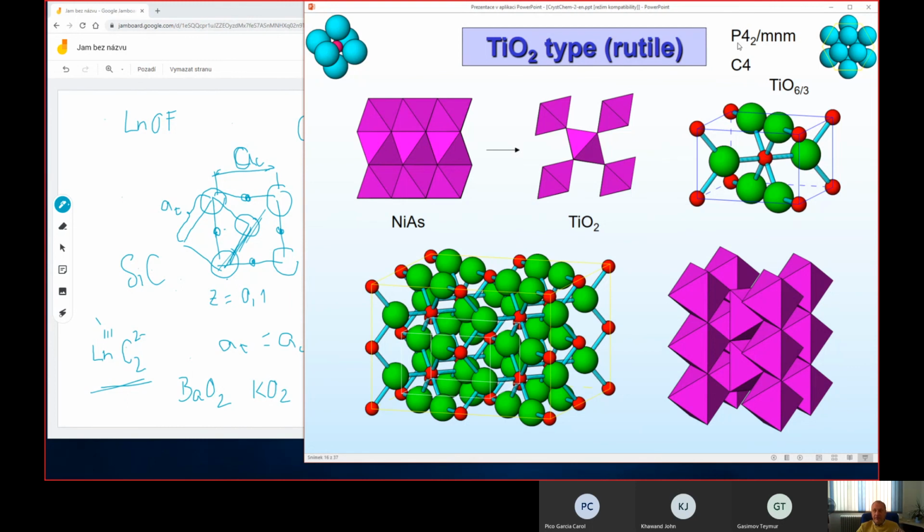But interestingly, the unit cell is not I, that means body centered, but it is primitive. The reason is that the oxygen atoms, which are here on faces and here in trigonal arrangement, don't fulfill this condition of body centering, and that's why the overall translational symmetry is primitive.